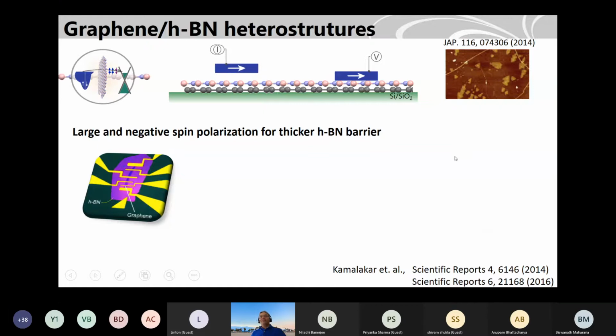Actually, in this boron nitride, it's not only monolayer. We also find in some places there are patches of bilayer, trilayer like that. And that actually we could use in our device structure. So we could put one contact on a multi-layer boron nitride with graphene below, and in the other part, the contact can be on monolayer or without boron nitride. So we could make multiple devices.